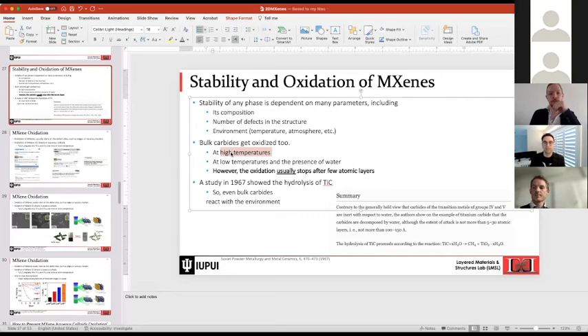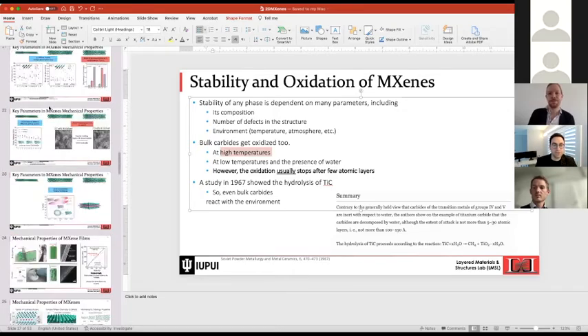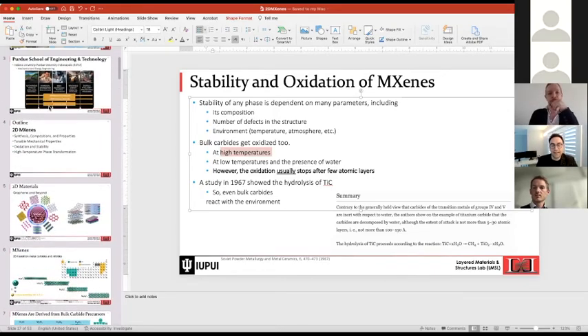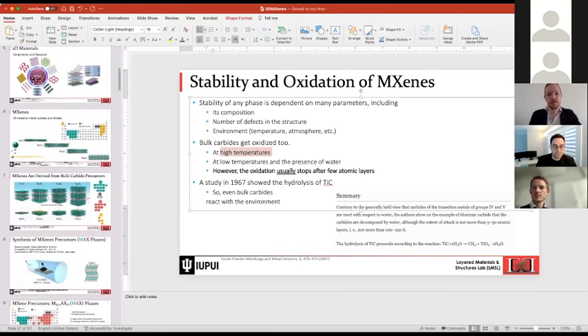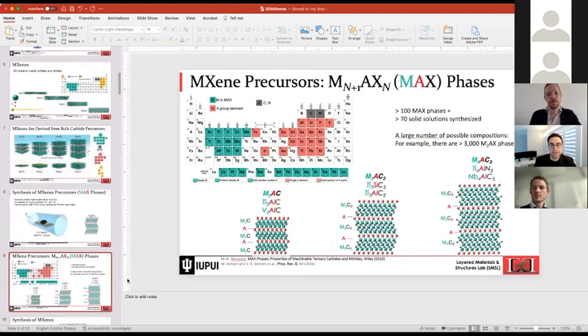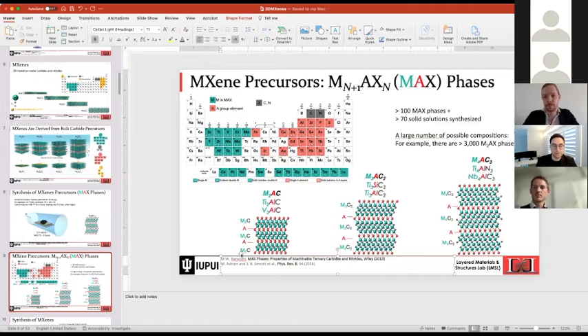Certain MAX phases, such as the aluminum-containing Ti2AlC, are known to be stable in terms of oxidation up to 1200 degrees C because they form a protective oxide scale around the Ti2AlC as a bulk. Obviously, if you do it as powder, the oxidation will be a lot faster, and that can be done even at lower temperatures such as 500, 600 degrees Celsius. If you're interested in the oxidation of MAX phases, again, you can read the MAX book or many of the papers of Professor Michel Barsoum that looked at the oxidation of different varieties of MAX phases at different temperatures.